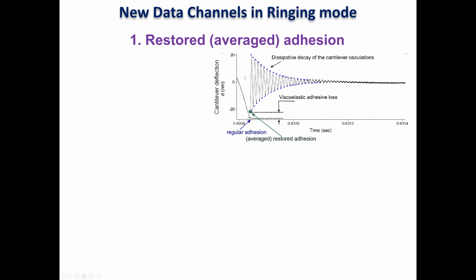First is restored adhesion. You'll see why it's called restored. We also call it averaged, but we'll see what it means. Regularly, adhesion is just a really tiny moment on the force curve at which the probe is no longer sustained by mechanical equilibrium contact with the surface and jumps up. This is a really sharp event, sharp in time. So you really have to have super high digitization to pick it up extremely accurately.